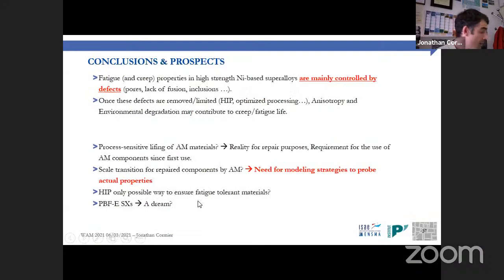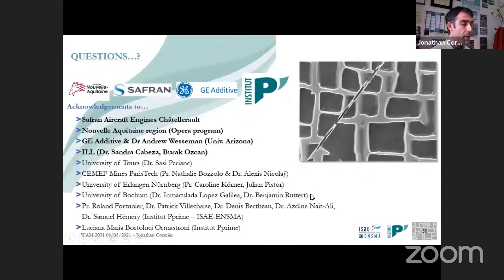And with this, I'd like to conclude my talk, just on time, by saying that for this class of material, high-strength nickel-based superalloys, the fatigue properties and, to a lower extent, creep properties are mainly controlled by defects inherited from the AM process, so typically pores and lack of fusions. Once these defects are removed or limited through HIPing, for example, then the anisotropy and the environmental degradation may contribute to creep and fatigue properties. And I don't want to read everything here. We really need to develop modeling strategies to probe the actual service mechanical properties. And with this, I'd like to thank all those colleagues, collaborators, and companies without whom this work would not have been possible.